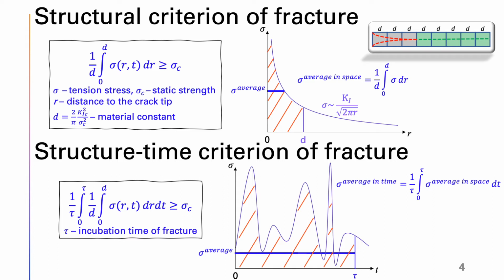So, the criterion states that the structural block of size d will fail if the average stress of this block exceeds the critical tensile stress of the material, sigma c. Average stress value is determined through the integral as shown on the slide. Structural size d is determined from the condition of the correspondence of the structural criterion to the classical approach within the framework of linear elastic fracture mechanics, and this parameter is a material constant. The formula for determining this parameter you can find on the slide, where K1C is the quasi-static critical stress intensity factor of the material.